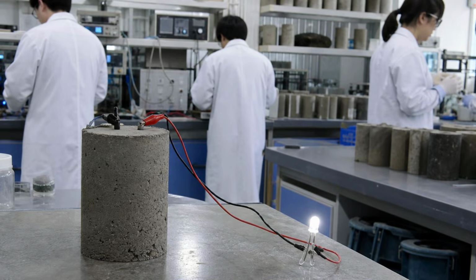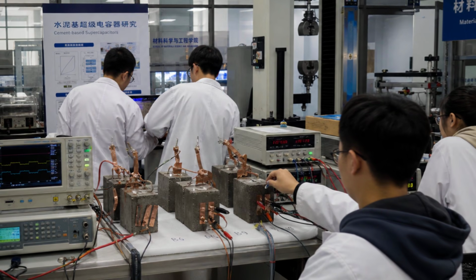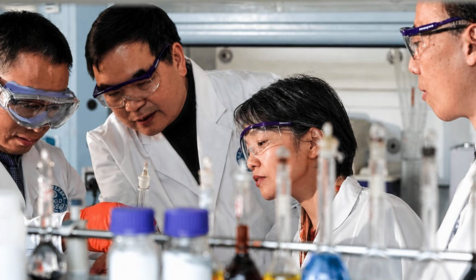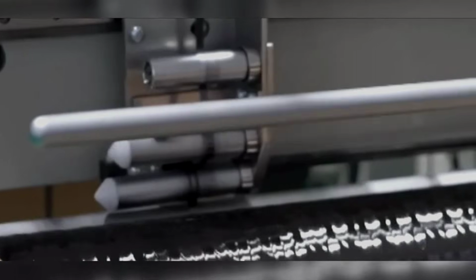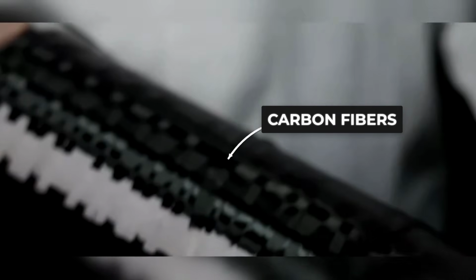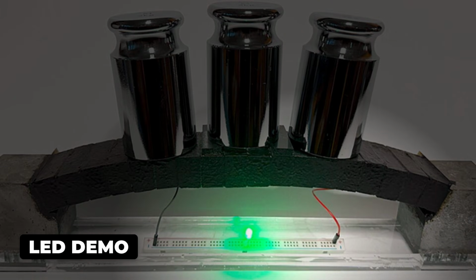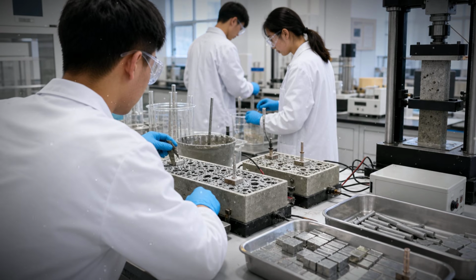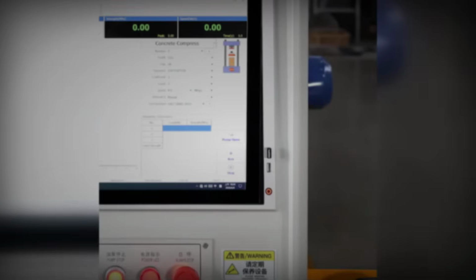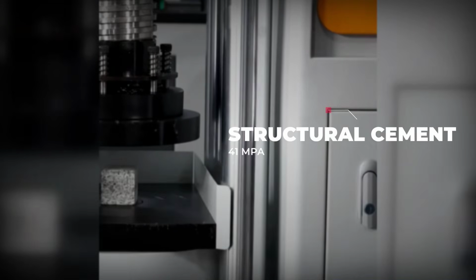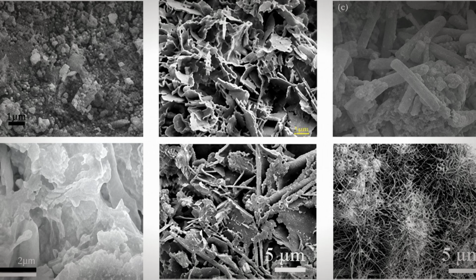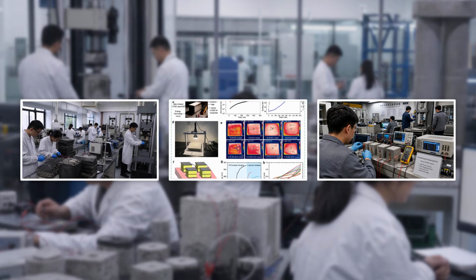Over the last 2 years, a wave of Chinese labs has been racing to turn cement into a supercapacitor, and the numbers keep climbing. One team building what they call cement-based structural supercapacitors, weaving carbon fibers and carbon nanotubes through ordinary Portland cement, hit a storage figure high enough to keep a red LED lit for more than 9 minutes off a single small block. And they're aiming it squarely at charging pavements, roads that carry their own power. Another group folded a zinc-based chemistry into aerated cement mortar to get storage and load-bearing strength out of the same pour. A third held the concrete's compressive strength up around 41 megapascals, genuinely structural grade, while still making it store charge. So the storing wall isn't one lucky paper. It's a whole field, and China is crowded into it.